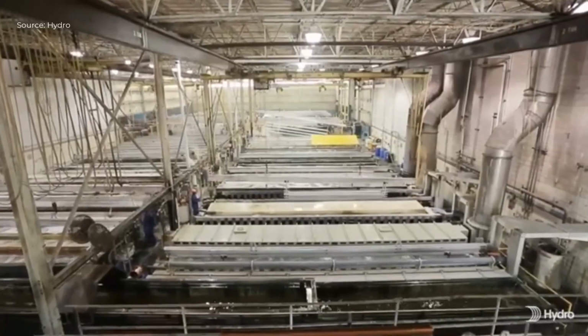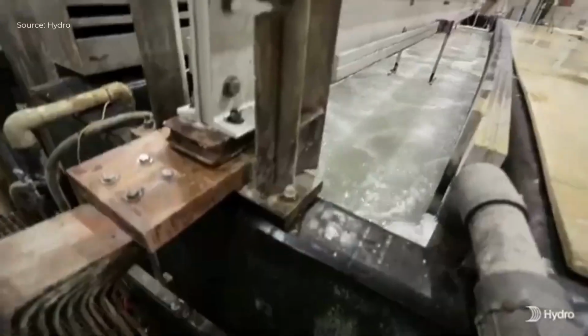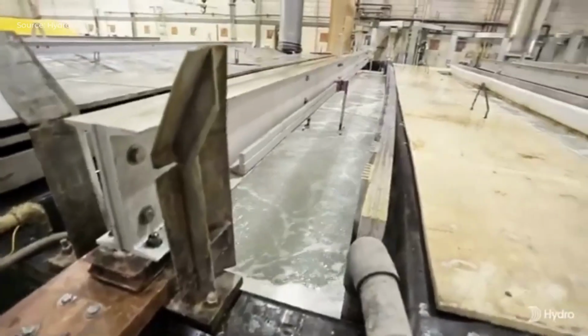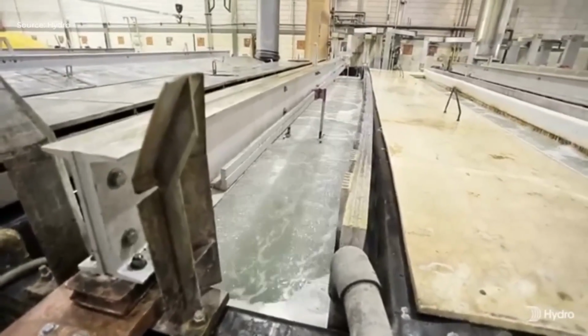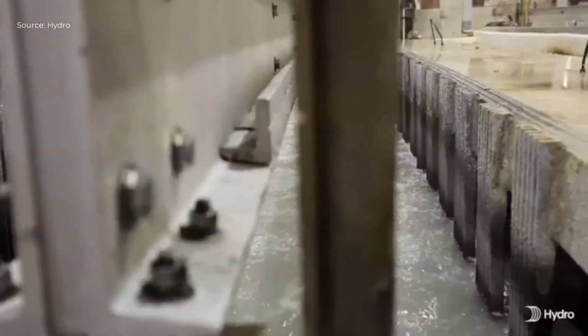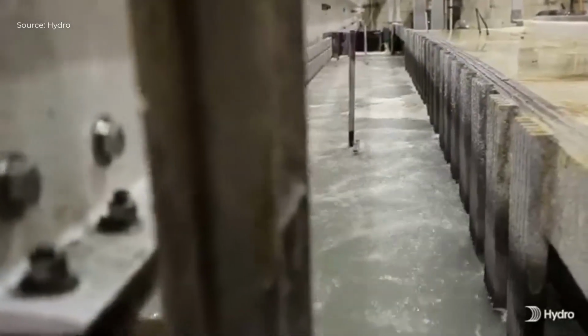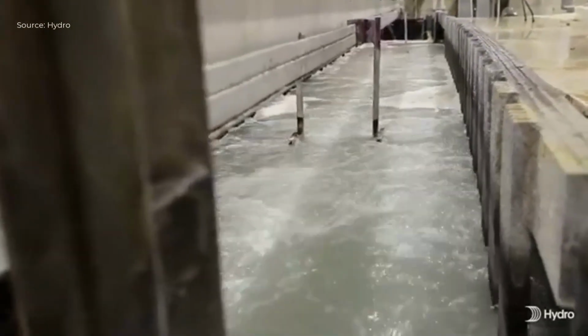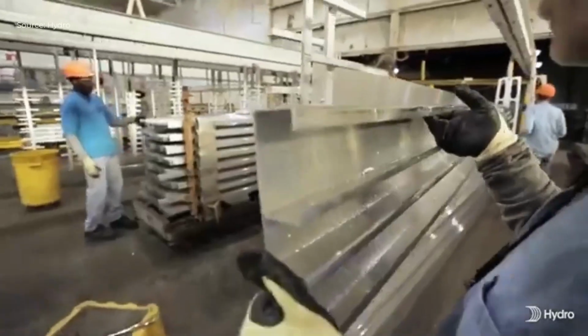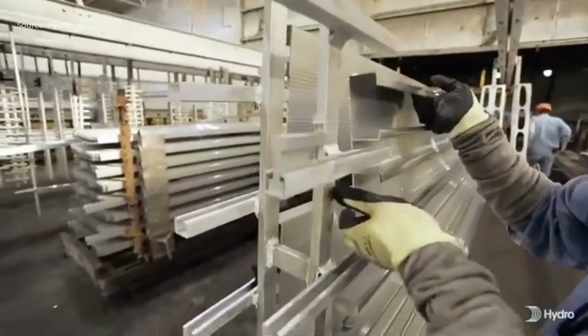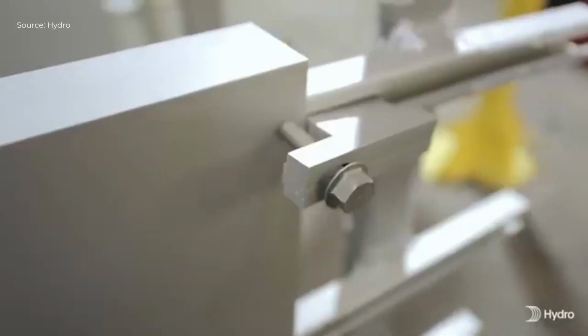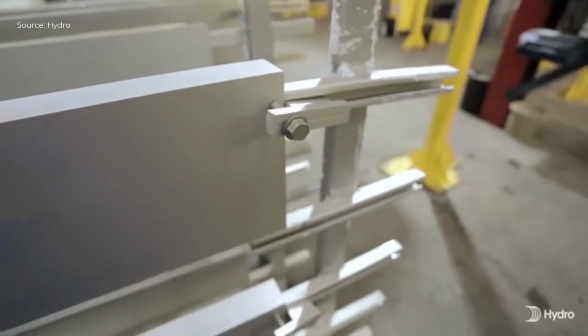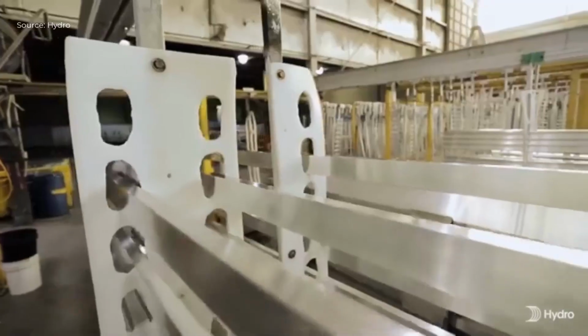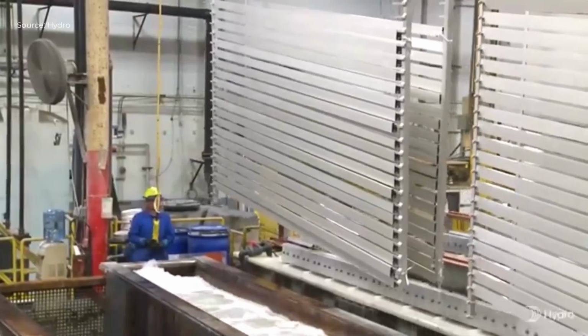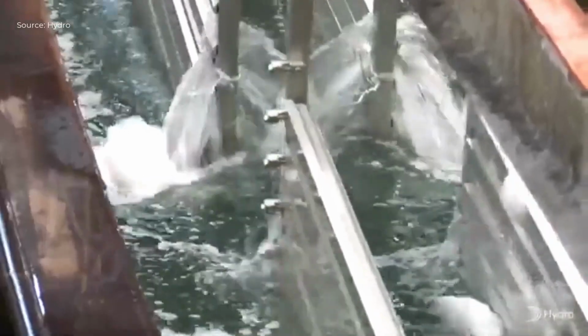Anodizing is an electrochemical process that transforms the surface of aluminum into a highly durable aluminum oxide layer. Unlike paint or plating, this finish is integrated into the metal, making it resistant to peeling, chipping, and corrosion. The process begins by immersing the aluminum in an acid electrolyte bath while an electric current passes through it. At low temperatures, this controlled oxidation forms a hard, porous layer that can be dyed or sealed for additional properties.